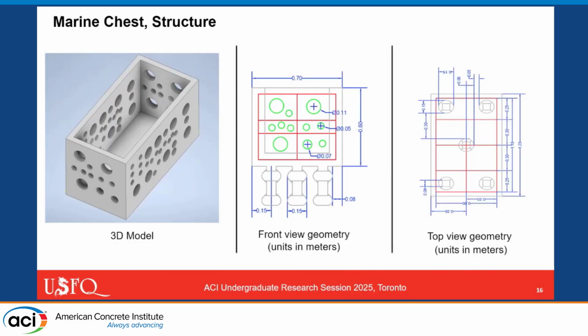After all of this, we decided to use the mix with 20% replacement of tricalcium phosphate and 20% replacement of calcium carbonate to create our artificial coral reef. For the design, we did a lot of research. We looked for a lot of shapes of artificial coral reefs, and also we wanted to see the conditions it needed to meet to be implemented on Isabela Island. We decided to have this hollow cube shape with a lot of holes because we needed water circulation. Here we can see the front view and the top view of the design.